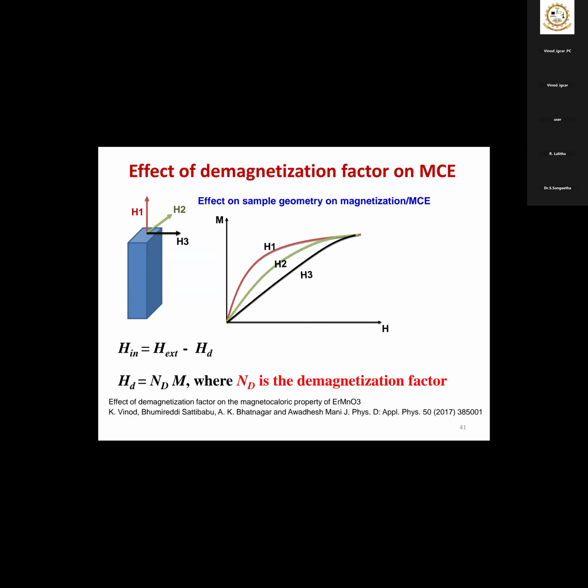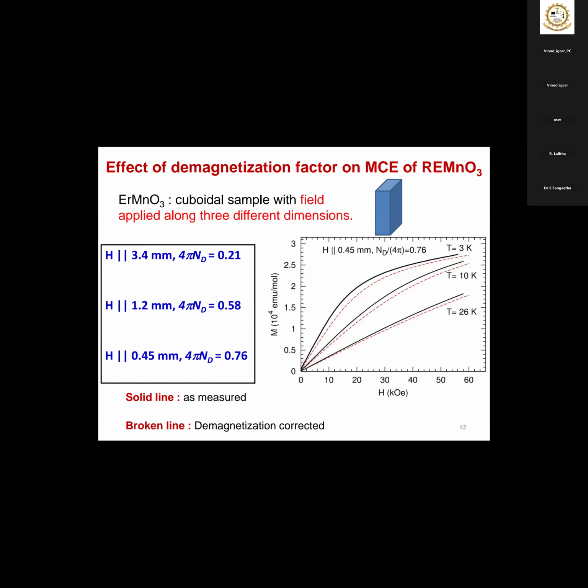I will brief like this. H external is your externally applied field. Because of the sample polarity developed inside the material, which is highly geometry dependent, it will develop a demagnetizing field H_D that will be opposite to the applied field. So in effect, the actual sample will feel only H internal, H_in, which will be dependent on the field geometry. I will just quickly go through because we want to know whether this geometry will ultimately affect your MCE.